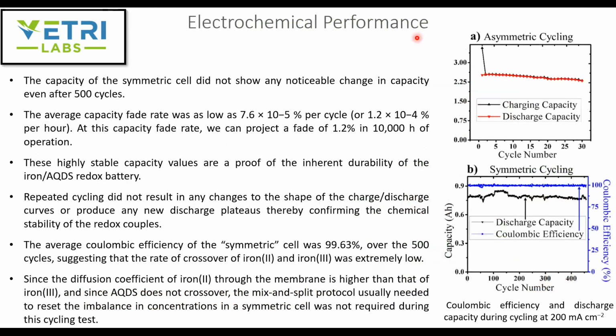To record the electrochemical performance, they did the capacity analysis at 200 milliampere per centimeter square. And as we saw on the earlier slide, the capacity starts to fade within a few cycles for the asymmetric configuration. Whereas for the symmetric configuration, there is no noticeable change in the capacity even after 500 cycles. They predict that the average capacity fade was around 7.6 times 10 to the power minus 5 percent per cycle. At this rate, they can project an overall capacity decrease of about 1.2% when operated for about 10,000 hours.